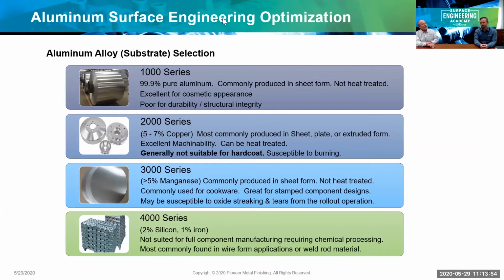The 1000 series of aluminum is 99.9% pure aluminum. The advantage to that being that there's no alloying metals put in the aluminum, and when you anodize it, you get a very clear silver appearance to it. The 2000 series of aluminum is usually used because it has a great ability to machine without wearing out tools. The downside to that aluminum, though, is the copper metal is added to it to improve the machinability. And copper is not necessarily a good friend for the anodizing process. There's a potential for burning, lower thicknesses are achieved, lower wear resistance, less corrosion.